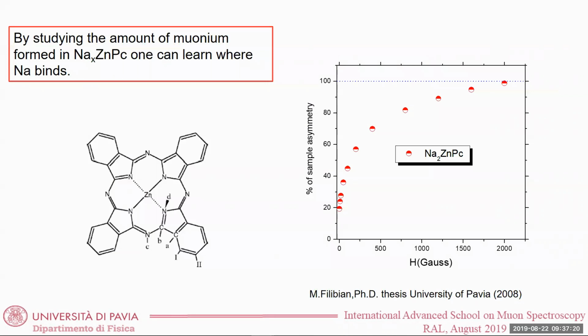What you end up with is that you form a lot of muonium. If the mu plus gets attached to one of these sites, and to know how much is the fraction of muonium that you get into this sample, what you can do is to study, for example, the recovery of the asymmetries in the magnetic field, and from this study you can have an idea about the fraction of muonium that you are forming.